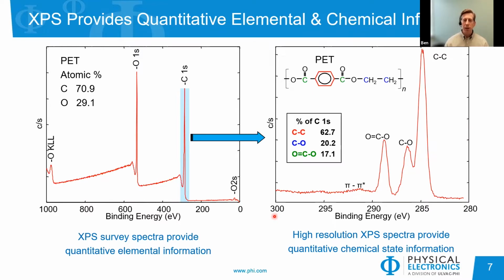As shown here on the right with this spectrum for PET, a polymer, we are looking at the carbon 1s spectrum, narrow scan or high resolution scan. And we see we have multiple peaks out of the original somewhat single peak that we saw in the survey. And so each of these are representative of a different chemical state, whereas carbon may be bonded to carbon here, bonded to oxygen, different bond to oxygen. So depending on the electronegativities of those bonds, you will see some different shifting of the peak, and we can use that to quantitatively investigate the type of material. And so in this case, we have a very large carbon-carbon peak, which would be similar to what we see here in this ring structure, and then some carbon-oxygen species, which match up with the species shown here in blue and in green. So this is where the power of XPS lies, to see chemical states and then chemical state changes as we process materials.